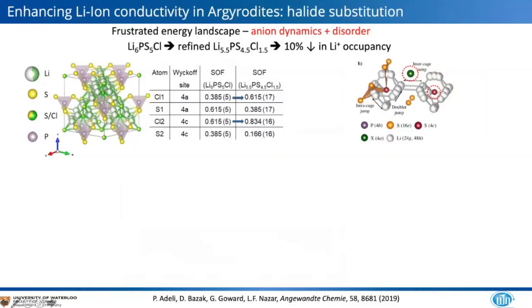So I'll just end off on some halide materials. Also an argyrodite, starting from this chloro-argyrodite. The different strategy here is to increase the halide concentration in this lattice, which actually increases vacancy. So whereas in the case of the antimonides, we have a lithium-rich argyrodite, in this case, we have a lithium-poor argyrodite. Again, as I said, it creates vacancies on the lithium sites, about 10%, and it makes the material chlorine-rich.